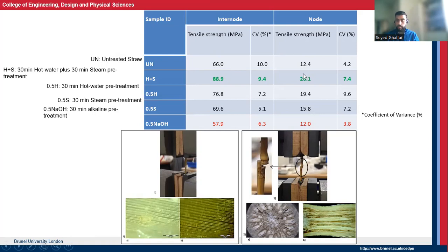So that's why it is a defect. It could be a defect in the context of a biocomposite. We came up with a treatment which I called H plus S, which is essentially 30 minutes of hot water washing plus 30 minutes of a steam pre-treatment for the straw. And you can see that it substantially improved the tensile strength of both node and internode, from 66 to 88.9 MPa for the case of internode, and for the case of node from 12.4 MPa to 20 MPa.